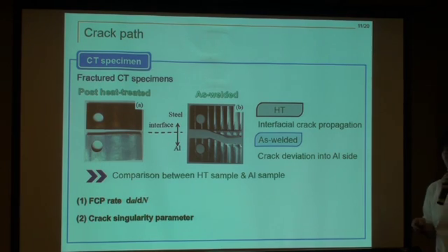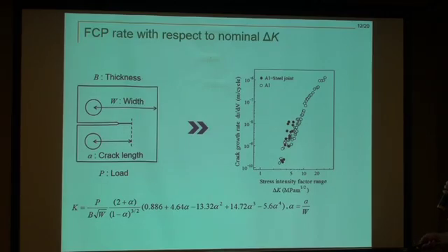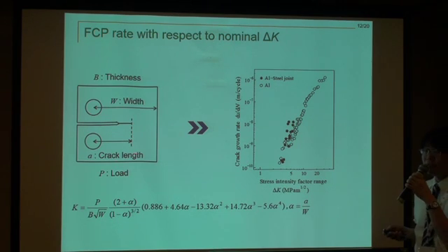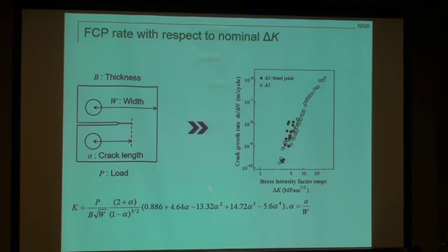So hereafter, I'm going to talk about the comparison between the heat-treated sample and the aluminum base sample. We relate the FCP rate with respect to the crack singularity parameter. We used the very standard CT test specimen, and in this specimen, usually the stress intensity is calculated using this approximation equation. However, in the so-called bi-materials with different elastic moduli, the stress intensity becomes quite complex, and the stress intensity cannot be calculated using this equation.